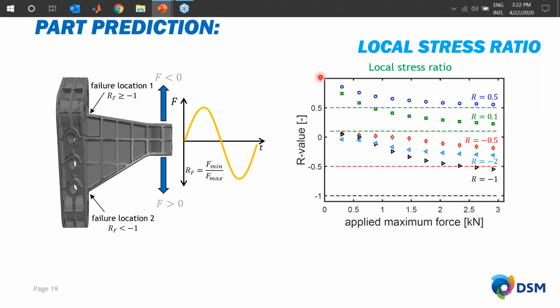And this is once more highlighted here on the right, where you plot the R value versus the maximum applied load, for different R values, but this black one is an example for R = -1. You see that we think that we apply R = -1, when in reality the R values are somewhere between slightly above 0 up to -0.5. So you really have to take this into account. The deviations can be really big, depending on the geometry.